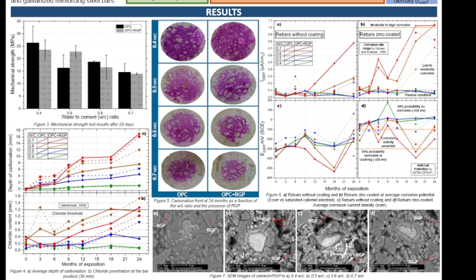This can be seen quantitatively in figure 5, which shows that at 28 days, mixtures with RGP offer slightly greater protection against carbon dioxide. Although the difference in protection is more comparable between water to cement ratios, with the uncolored areas being those that have already been penetrated by contaminants. In other words, we obtain a high densification of pores at a lower water to cement ratio.